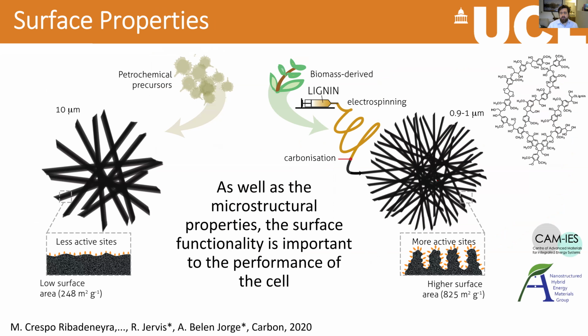And we're also looking at changing the surface properties of these electrodes using electrospinning to make electrodes from other materials, such as lignin, for example, which is a biomass material. It's actually a byproduct of the paper industry, and so it's very green, as opposed to the petrochemical derived PAN polymers. But also we can tune the surface of these fibers. So even though we're carbonizing these, turning them into graphite, there still remains some surface functionality, some oxygen groups, for example, on the surface, and we can use this to tune the catalyst of the reaction, and therefore minimize these activation losses that I talked about earlier.